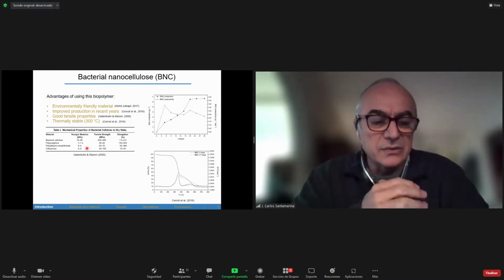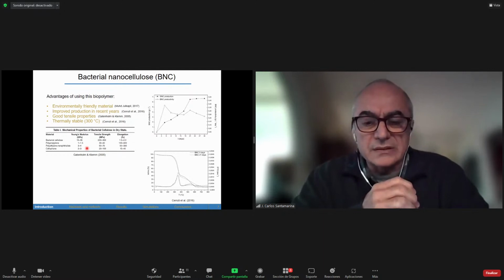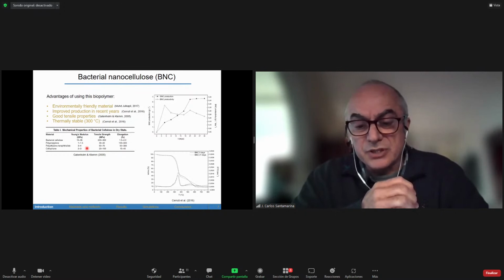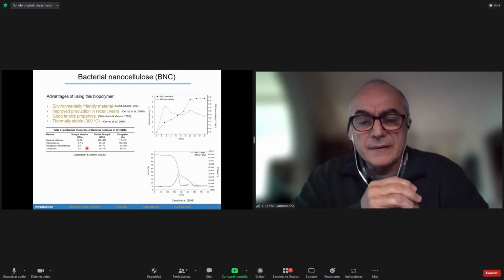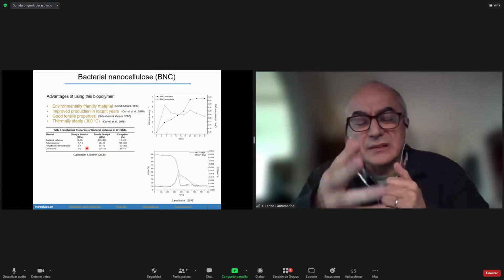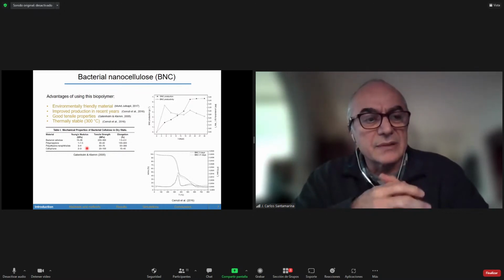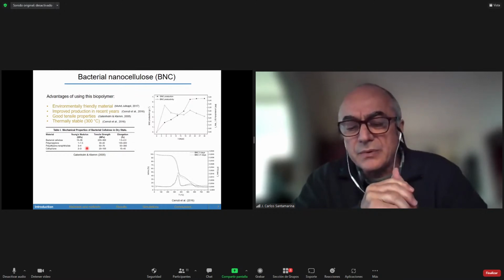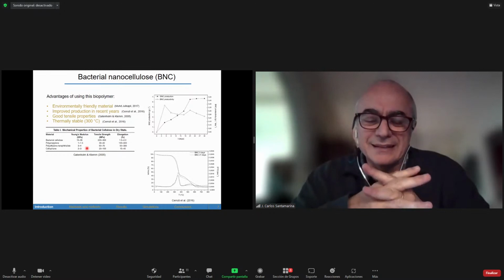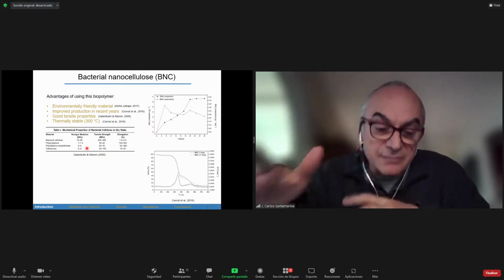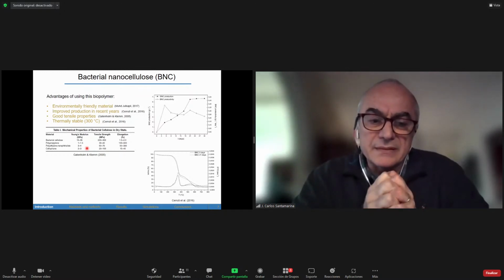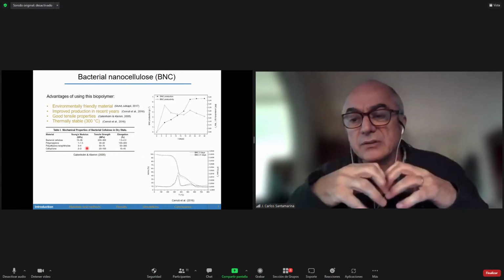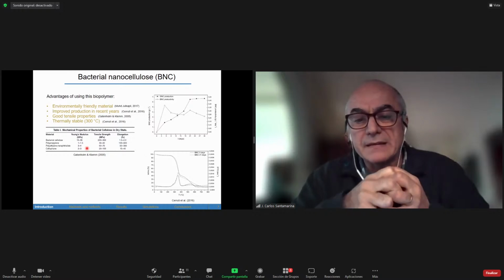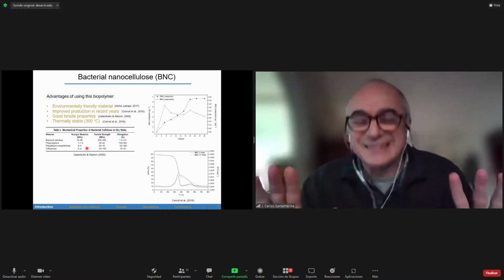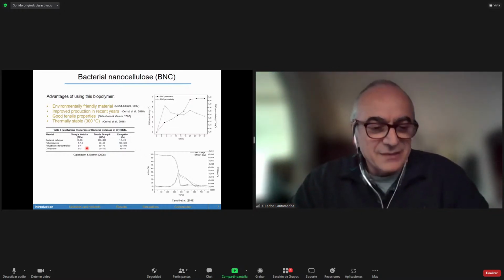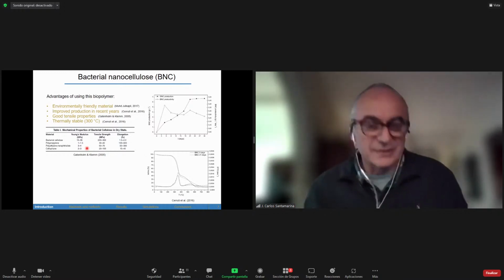For example, this likelihood that cellulose, while it is very stable in water in general, has relatively high solubility at pH 10, and you are at very high pH with hydrating cement. And in fact, in none of your SEM images, there is one that shows some fibers when cement is involved, but they look different. It's not the original fibers. So, just a thought. And all these issues of osmotic effects and double layers and the surface charges could probably help you bring an alternative hypothesis that could bring clarity to your results, which I find fascinating, even though I am outside this field. So I'll close with that, my part of my comments.